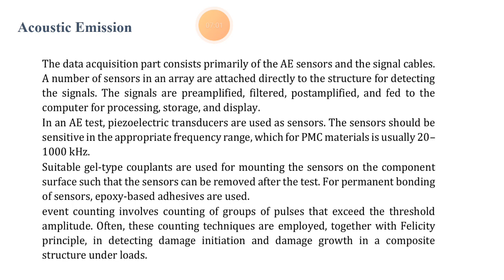The sensors should be sensitive in the appropriate frequency range, which for polymer matrix composite (PMC) materials is usually 20 to 1000 kHz. Suitable gel-type couplants are used to mount the sensors on the component surface such that the sensor can be removed after the test. For permanent bonding of sensors, epoxy-based adhesives are to be used. Event counting involves various groupings.